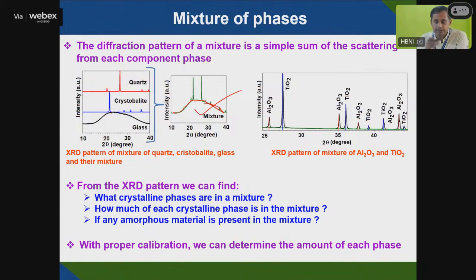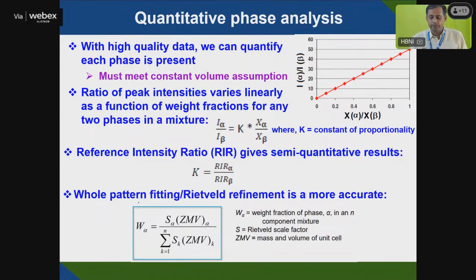You can analyze what percentage is amorphous and what the percentage of crystallinity is. If you see the Al2O3 TiO2 mixture phase, this is Al2O3 and this is TiO2, you can find out the composition. And if you do the XRD carefully, you can find that out too. So you can find out what crystalline phase is formed, how much of each crystalline phase is in the mixture, what the component of Al2O3 is and what the component of TiO2 is. If there is an amorphous phase, like silica here, you can find out whether it is present or absent. With proper calibration you can find out each phase, and that calibration can be done using a known element with high quality data. We can quantify each phase.